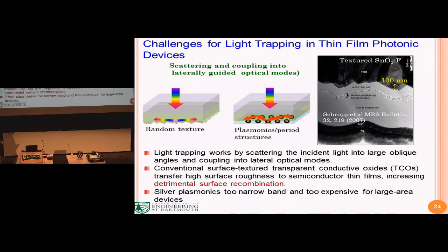Conventionally, people have done this in several ways. One way is to use a textured transparent conductive oxide. That's a heavily doped oxide semiconductor material. This material is transparent, and it serves as an electrode for the solar cells. You can also control the deposition condition and etching to create some surface texture. When you have the surface texture, when the sunlight comes in, it's going to be scattered sideways. So that increases the optical path length of light inside the material.